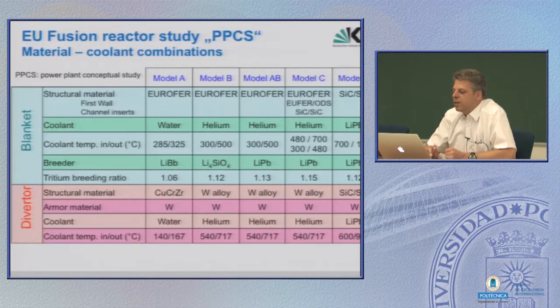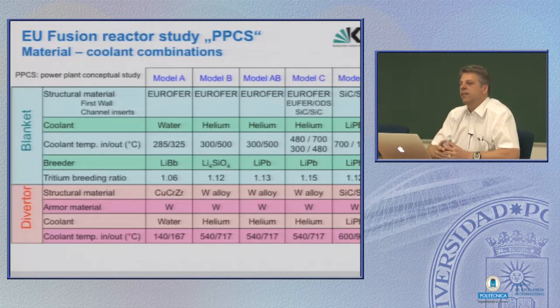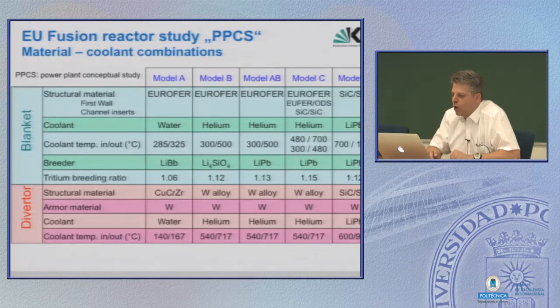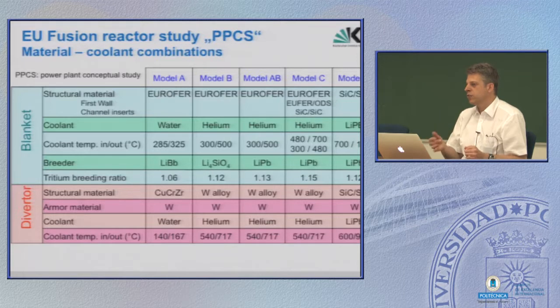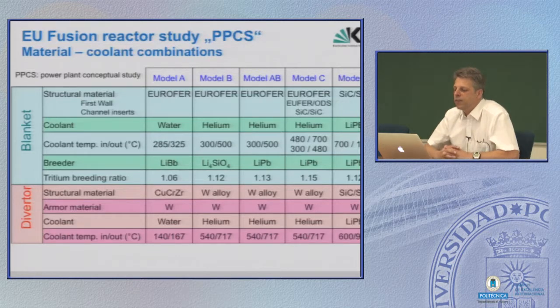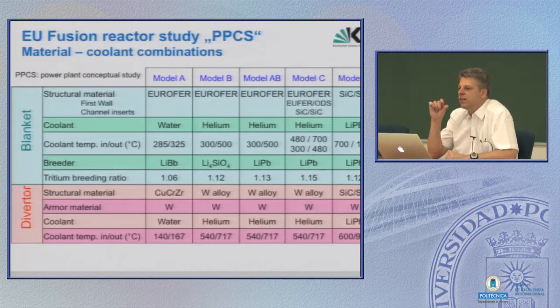And here the beneficial thing is that you could raise temperatures up to 500 C, and this would mean that the steel is operated in the safe region where no hardening or at least only a small amount of hardening and embrittlement occurs. Then there are some rather ambitious models which would like to have liquid metal cooling, but you know, high magnetic fields, which we of course have in the magnetically confined tokamak, and liquid metal leads to so-called magnetohydrodynamic effects due to eddy currents and so on. So that's not the very best thing to have. At least you need electrically insulated pipe systems where the liquid metal flows, and so you could not use steel or any metal for structural materials.